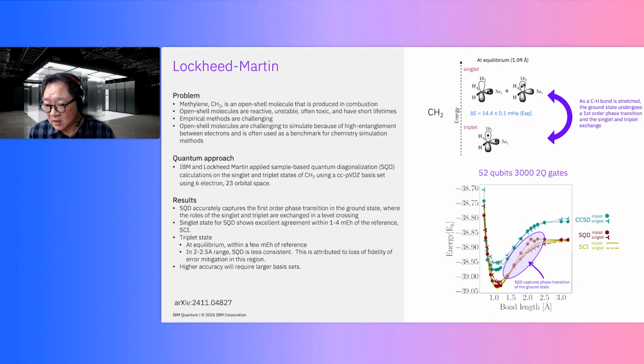And what you see in the purple area is that the SQD captures this phase transition at equilibrium at the bottom part of the curve, around 1.1 angstroms. You can see that the singlet state, in the round circles, has a lower energy than the triplet state, in those three-legged icons. And then as you stretch the bond length, you can see that the two lines cross, and that the singlet state has a higher energy than the triplet state. And so the SQD is correctly capturing this phase transition.